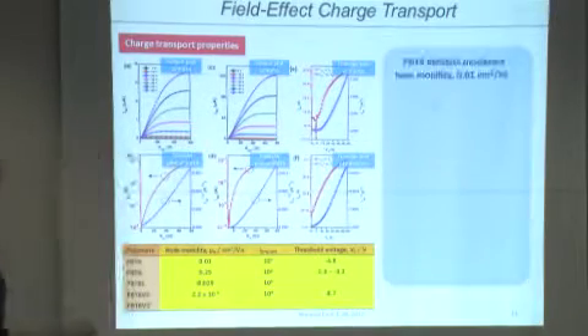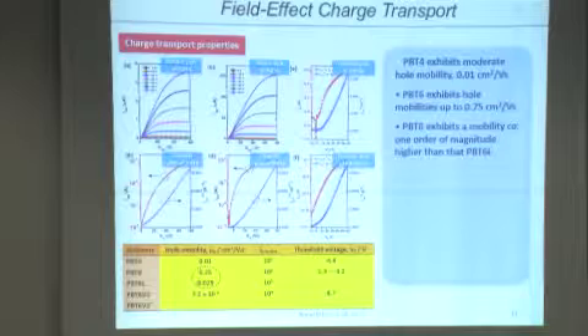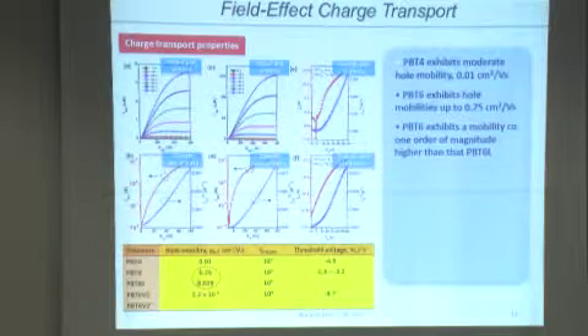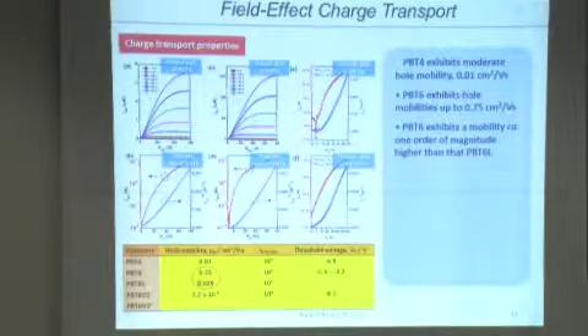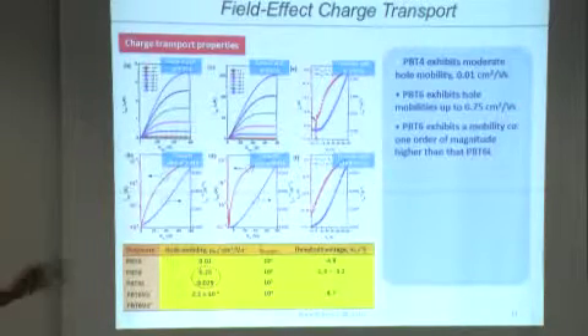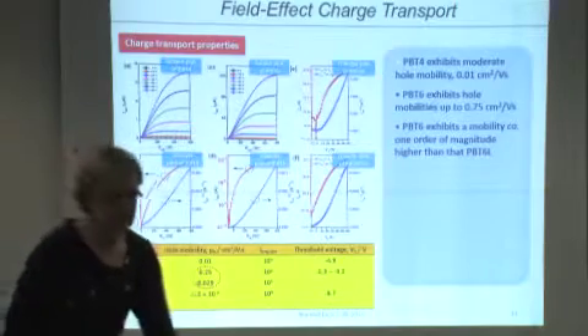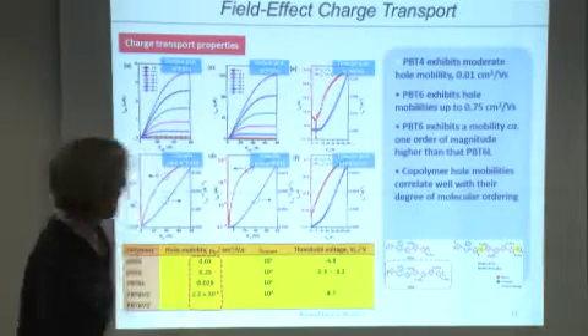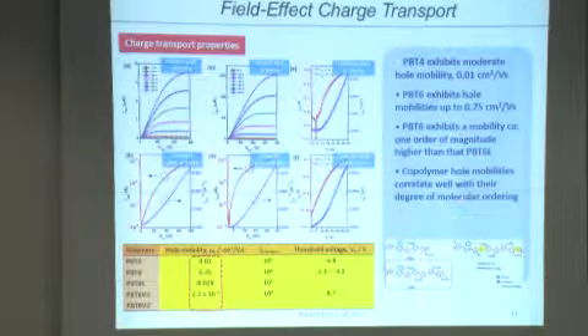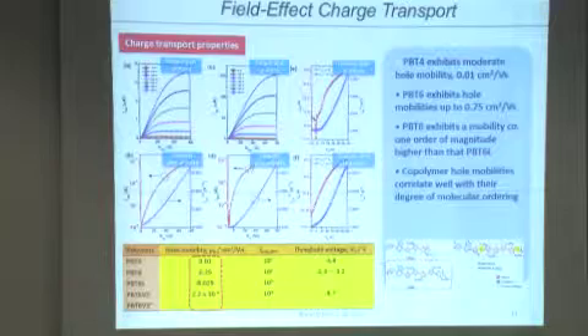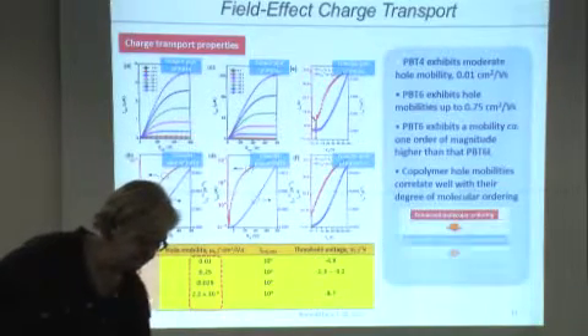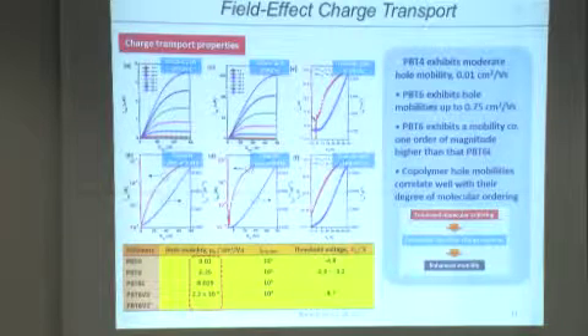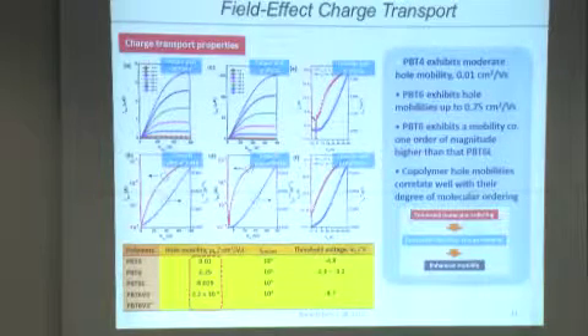So what we believe, we're able to get good charge transport characteristics within this material. The hole mobilities are up to about 0.75 centimeters squared per volt second. The higher molecular weight material has a mobility about an order of magnitude higher than the lower molecular weight material. The copolymer hole mobilities correlate with molecular ordering. And basically, we are able to tune mobility by working with the molecular structure of the material.